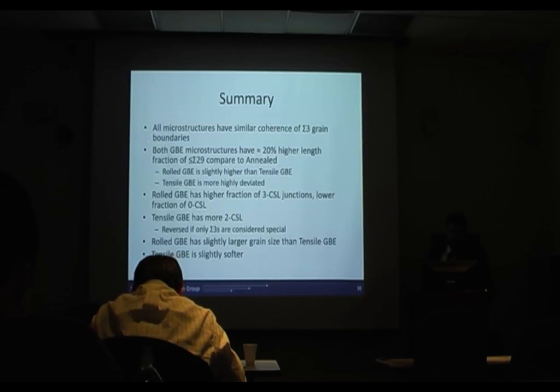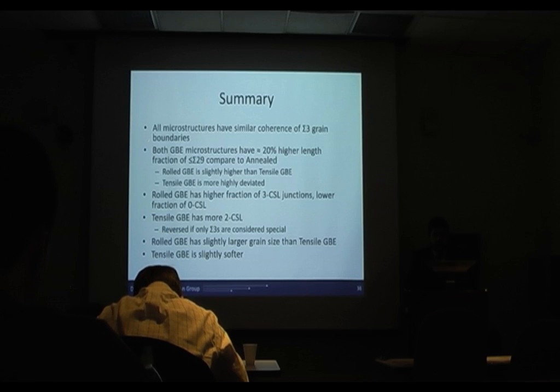So, quick summary about this. All microstructures have similar coherence to the sigma 3 grain boundaries. Both GBE microstructures have about 20% higher length fraction of CSLs, and the roll GBE is a little bit higher than tensile GBE, and the tensile GBE is also more highly deviated. The roll GBE has a higher fraction of 3 CSLs and lower of 0 CSLs. Tensile GBE has more of the 2 CSLs, but less if you're only considering the sigma 3s. And then the roll GBE has a slightly larger grain size than the tensile GBE. All of that indicates that the rolled GBE should be a little bit better in corrosion than the tensile GBE, based off the published literature.